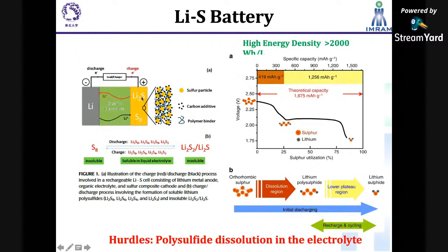In the case of lithium sulfur battery, organic electrolyte is sandwiched between lithium and sulfur. During charging and discharging, sulfur will change to lithium polysulfides, and then finally lithium sulfide, Li2S. The one problem with this lithium sulfur battery is the formation of these intermediate compounds. These intermediate compounds are soluble in the organic electrolyte, and finally there are some insoluble species. These start to deposit on the cathode material. Therefore it decreases the active material, or it decreases the performance with longer cycle time.